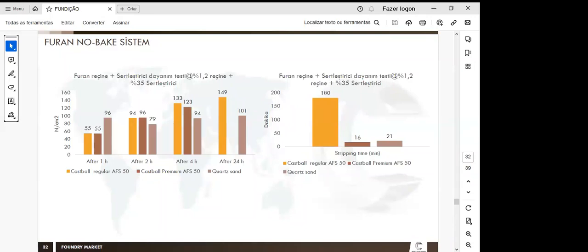We have here some results with furan resin. We can see in this first example, okay, mixtures of Castboll and silica sand with a typical resin used in Turkey. With Castboll sand, the resistance increases slower, okay? After 1 hour, the resistance of the Castboll mixture is lower than the silica sand, but after 2 hours, the mixtures with Castboll reached a great strength. This is the behavior that differs between Castboll and silica sand for this type of resin.